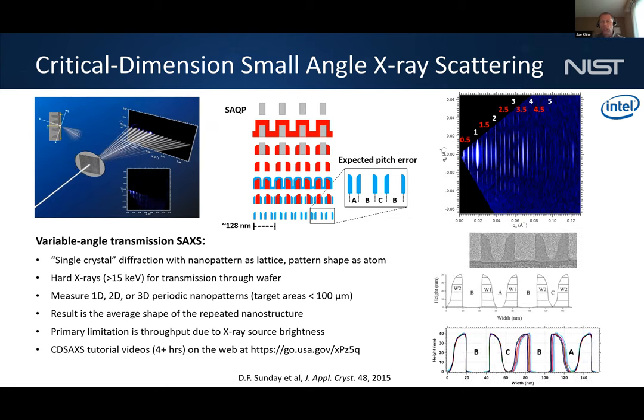And so with this particular case, you can see there's a cross-sectional TEM. And for the shape models that we use, typically you use trapezoids so that you have an analytical form for the Fourier transform. And you can then, as I said, adjust it until it fits the data well. Intel provided us a sample set where they varied the A and the C ratio, and you can see in this particular case, we're able to get about nanometer resolution on what these different pitch errors were. But of course, this was at the synchrotron.